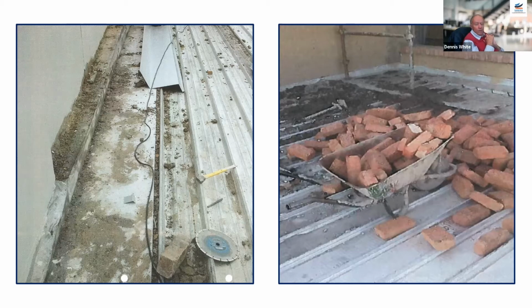And of course, which is fatal is where the mortar has not been cleaned off whilst it's still wet and it's been allowed to dry and harden, because then they mechanically remove it. And that's like taking a wire brush onto your metal surface. And bearing in mind, most metal surfaces are only about, well, depending on the source of your material, they could be as thin as 10 microns, but the majority of the products specified in the country is normally around 19 microns thick.